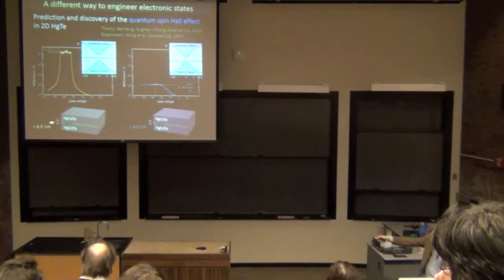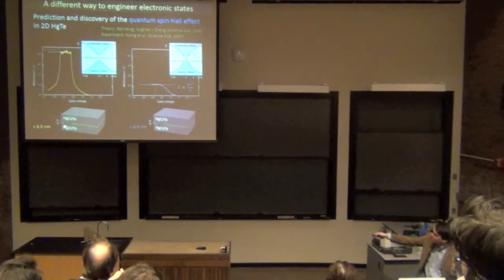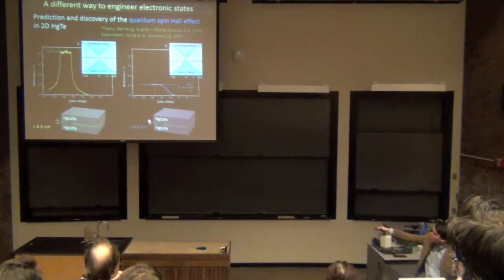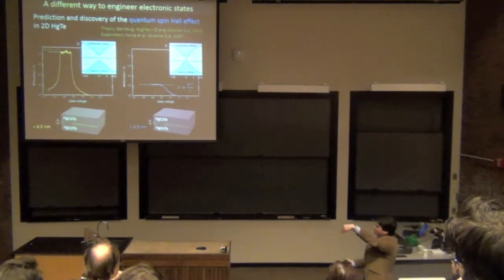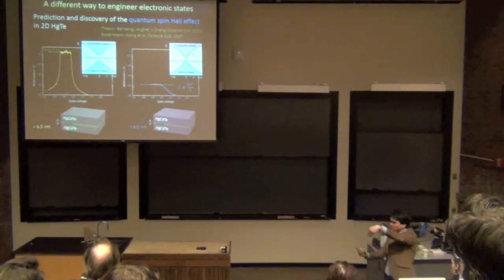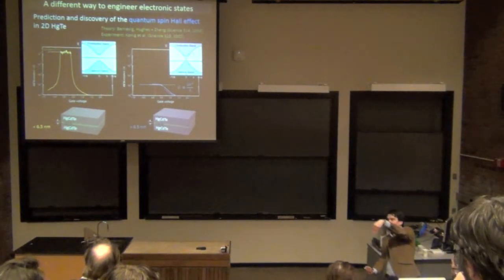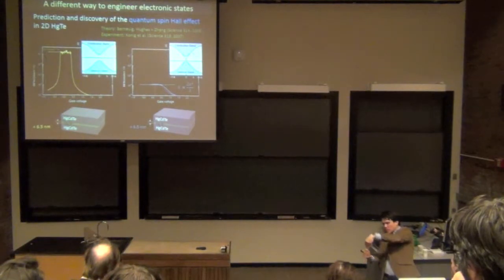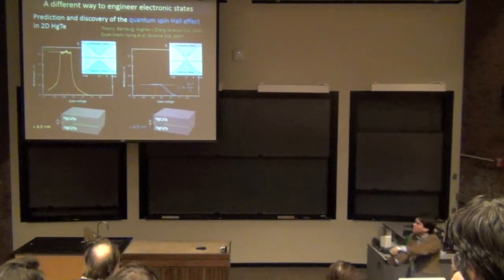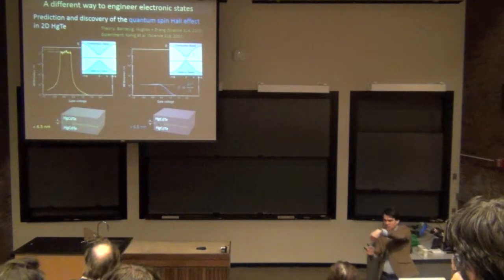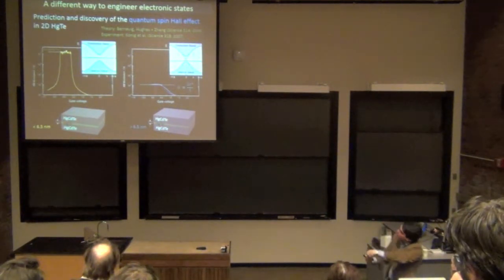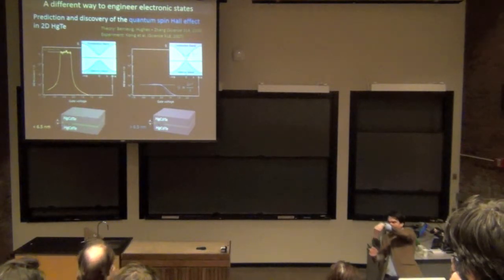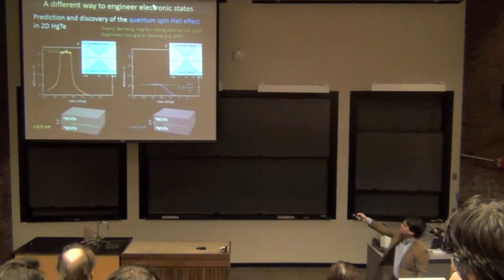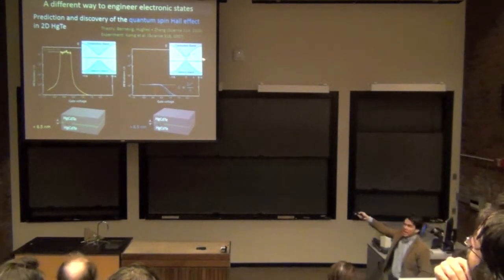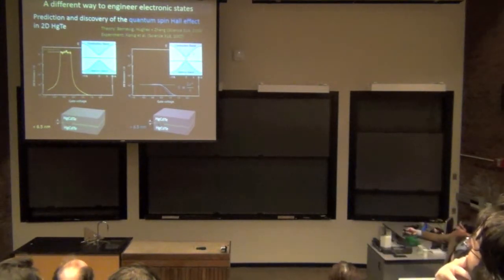The only difference between this picture and this picture is that we made the thickness of the well slightly different. What's happening is that as you tune the thickness of the well, the two bulk bands come together and touch, and at the point at which they touch, the system essentially behaves like graphene. And then as you make the system even larger, the bands open up again, but when they open up again, you're left with these interesting edge states on the edge of the sample.